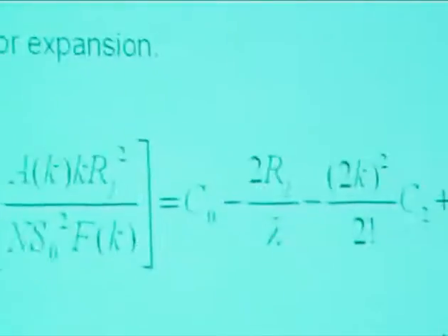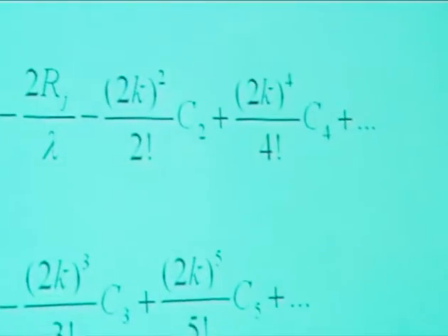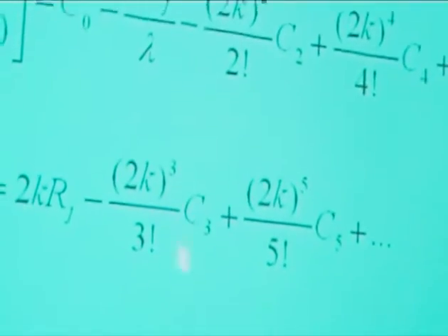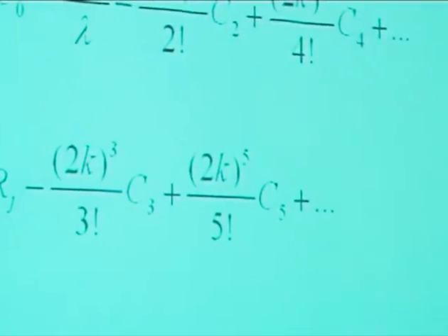And this is the so-called cumulant expansion, or the Taylor expansion. You go to the cumulants, so the 0, the second, the fourth cumulant, and in the phase factor you have the 1, the 3, and the 5. And you can now analyze them. The classic analysis only has this and this part, and doesn't have the C2, C4, nor the C3 and the C5. And the question is, do we need to add them for a small metal particle? And the answer is yes.